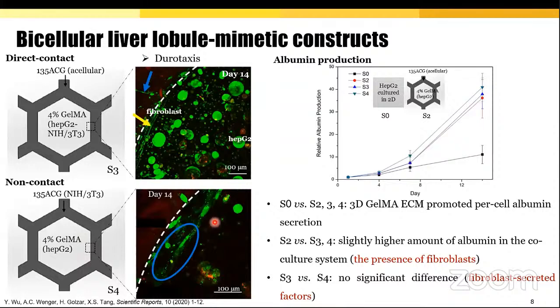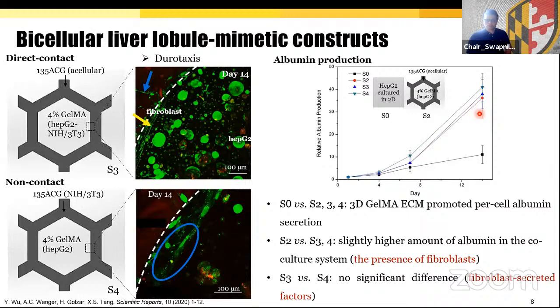Besides the study on cell morphology and proliferation, albumin secretion, a liver-specific marker, was measured to assess HepG2 function in 2D, 3D monocellular, and 3D bicellular co-culture systems. Compared to 2D system, albumin secretion went up dramatically in all 3D cultures, indicating 3D GelMA ECM promoted per cell albumin secretion significantly. From day 7 to day 14, we also observed that higher amount of albumin was produced in the co-culturing system, which could be explained by the presence of fibroblasts.